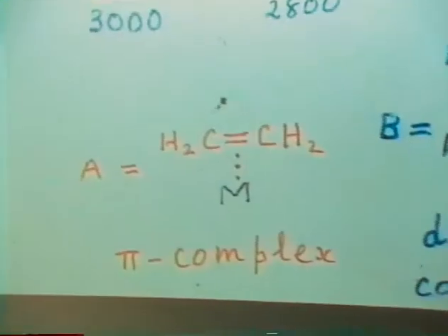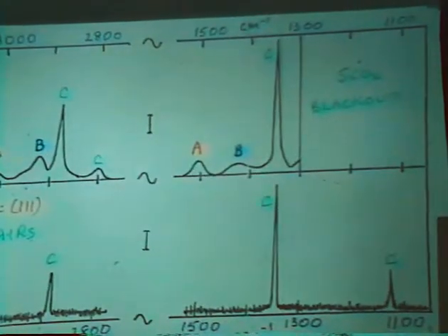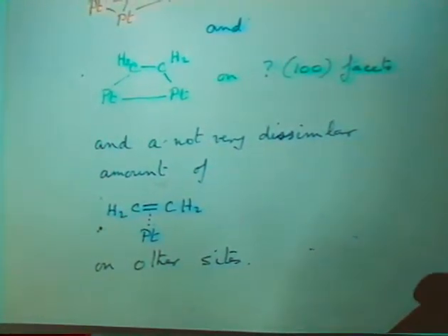So now we have the three species identified, the two strongest ones being none of the species we originally looked for, being the ethylidyne spectator species, the next two being the di-sigma species, and the other two being the pi complex. So, for ethylene on finely divided platinum, we have approximately equal numbers of ethylidyne and di-sigma, simply because of the intensity relationship in the conversion to ethylidyne, and probably a not very dissimilar amount of the pi complex, because intrinsically the CH absorptions of olefins are weaker, as again Stan Francis showed, than those of alkanes.